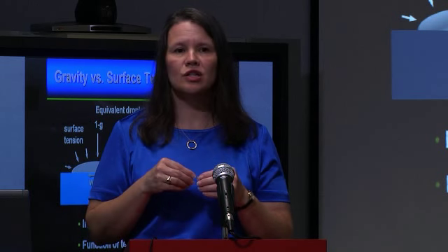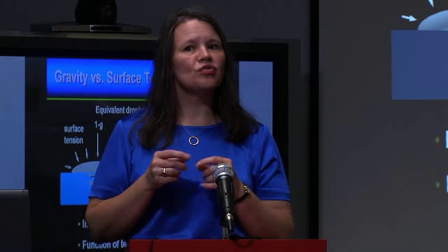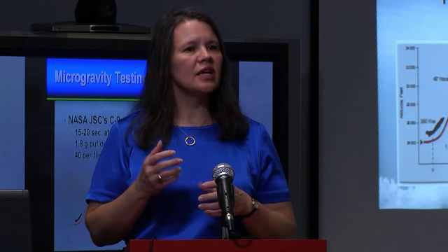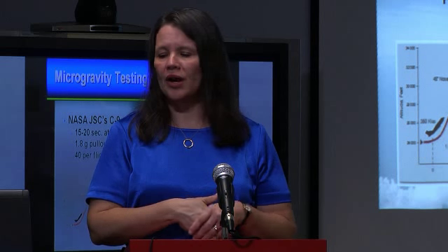Is that surface tension, you've got wetting forces trying to spread a bead out on the plate. And you've got surface tension that's trying to pull it together, and then you've got gravity that's pushing it down. And so our question was, how much is gravity helping us in this process? And how is that going to affect what we try to build in space versus things that we would build on Earth? Actually, some of these experiments helped us to understand the surface tension, which is now helping us to improve the process control on the ground. And so, even though this was for space, it's got real value here on the ground.